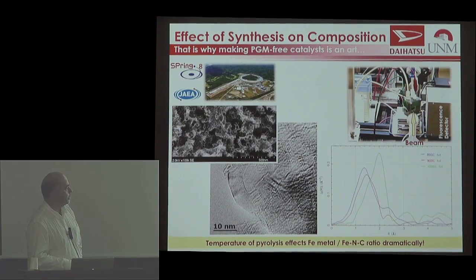The conditions of the pyrolysis are critically important for formation of this catalyst. Here is a very simple illustration: if you have a catalyst that is pyrolyzed at temperatures below, let's say, 1000 degrees for this particular system, you obtain an iron-nitrogen bonded catalyst. But if you pyrolyze a little bit more, or too much, or too long, you will obtain predominantly metallurgical iron or iron carbide in that system. So that is just a formal illustration, actually obtained nearby across the pond, in a different island here, that you actually need to arrest the pyrolysis before you arrive at a full metallurgy of the iron.